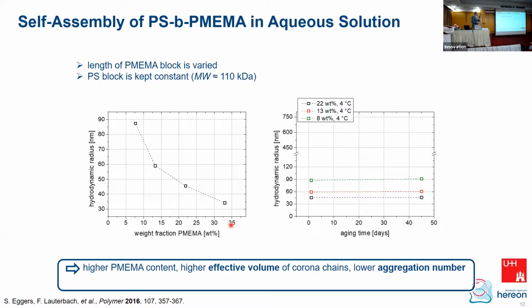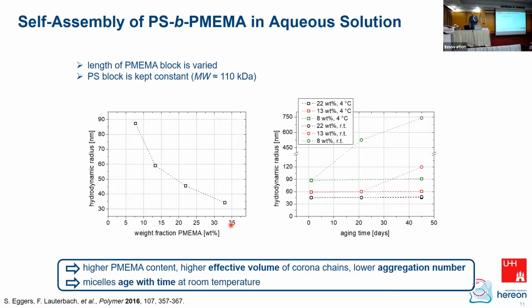So here you see for the different lengths of the polymer blocks at 4 degrees centigrade that we don't see any effect of time on the hydrodynamic radius, but when we have a slightly higher temperature, so more mobility, so to say, of chains, then you see that we get a certain increase of the aggregation size, and that again tells us that the whole thing is by no means really easily in equilibrium, but there's also still something going on, some reorganization of micelles and change in the aggregation numbers.